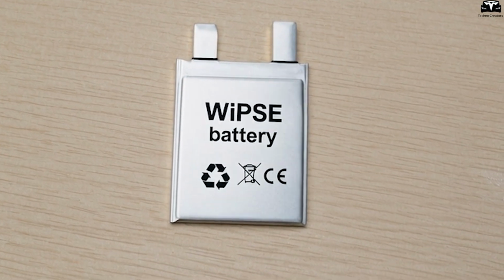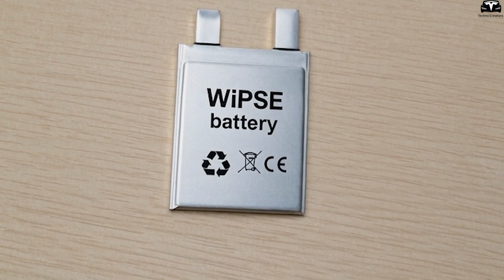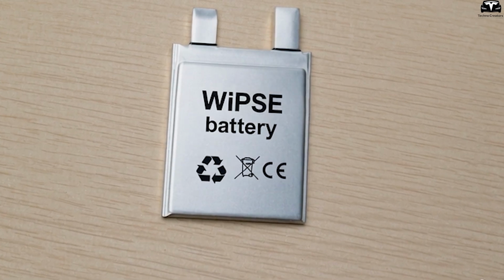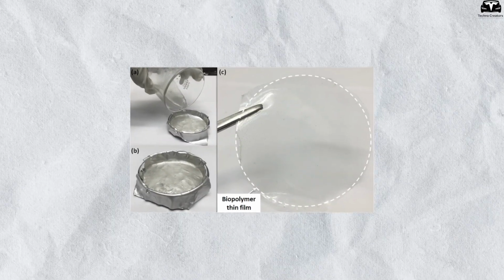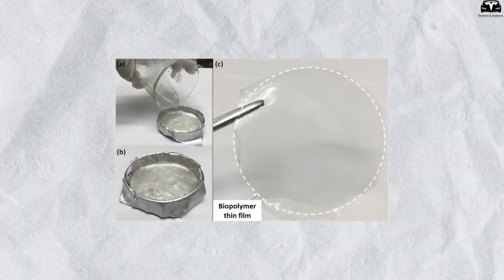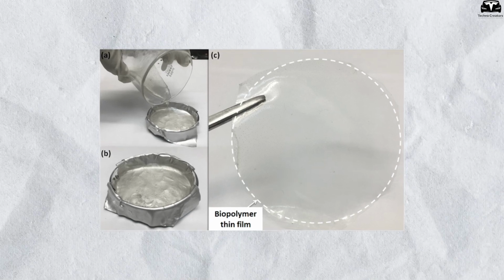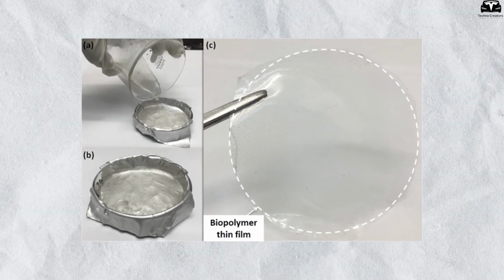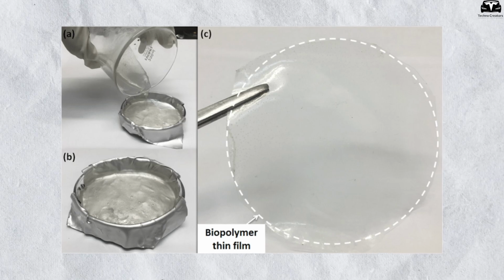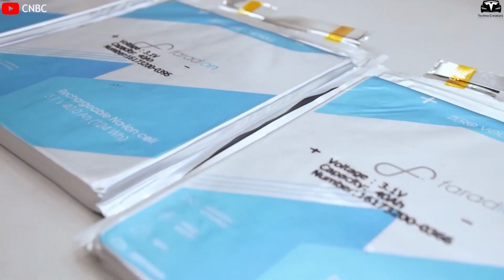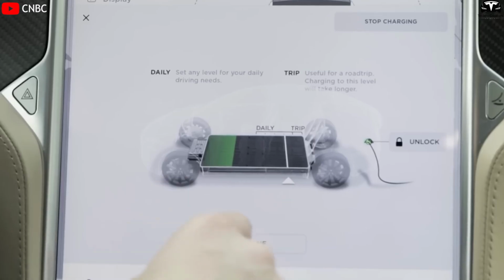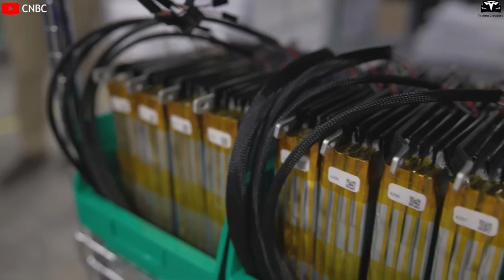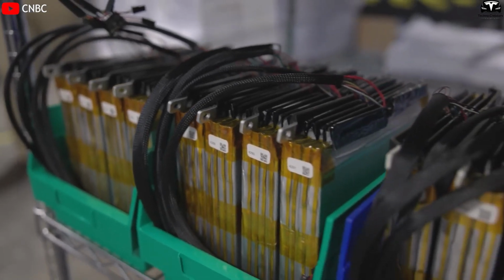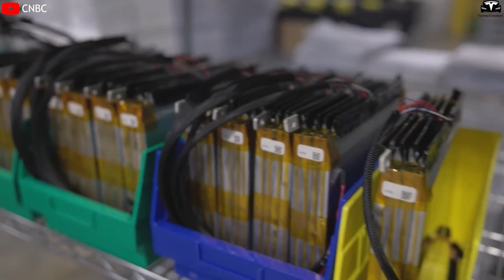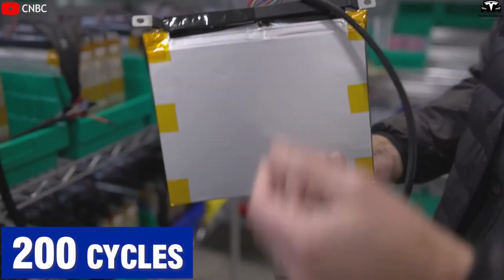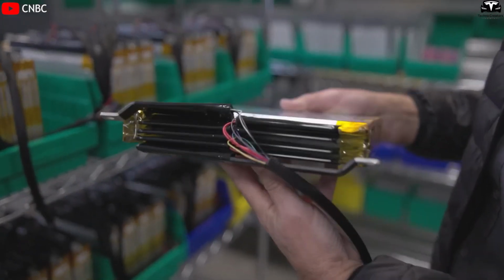Another advantage of WiPSE is its design flexibility. This electrolyte can be formed into gels or thin films, enabling applications in thin, flexible, or directly printed organic batteries using electrodes such as polythiophene, polyanthraquinone, or lignin. Tests combining WiPSE with these organic electrodes show capacity retention over 1,000 cycles without significant degradation, compared to batteries using traditional aqueous electrolytes, which only retain about 200 cycles before capacity drops by more than half.